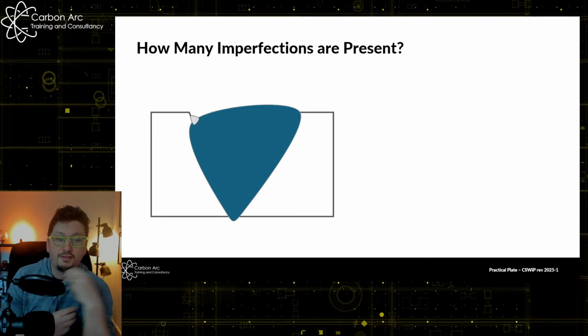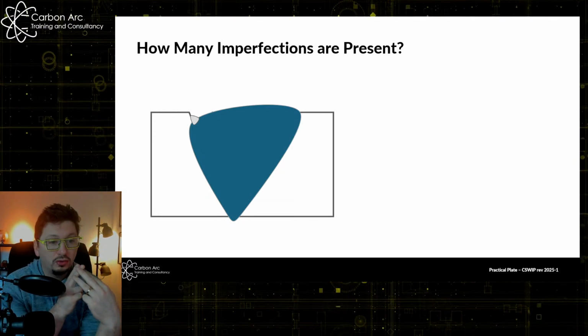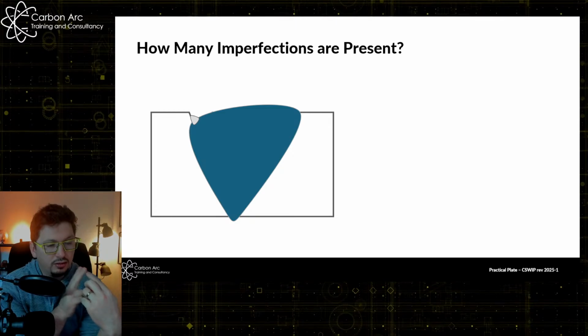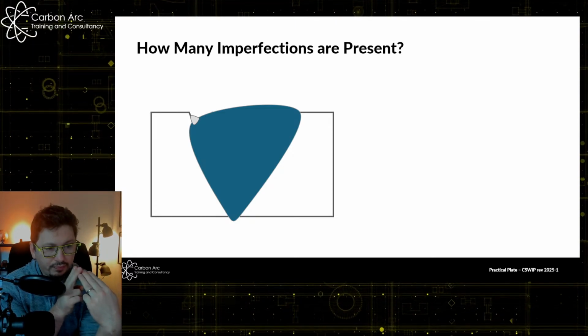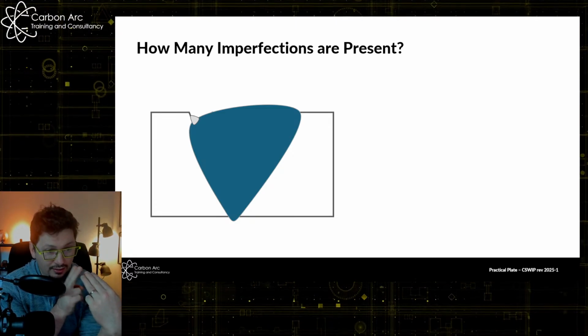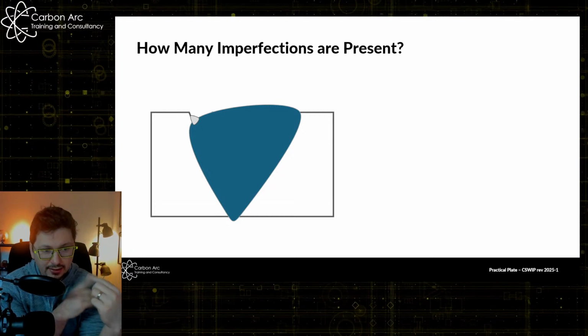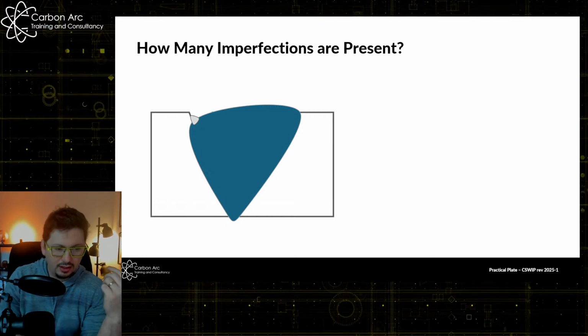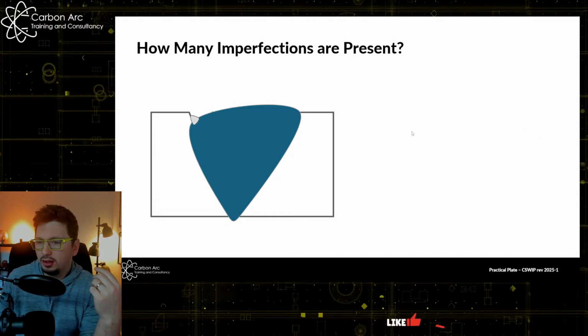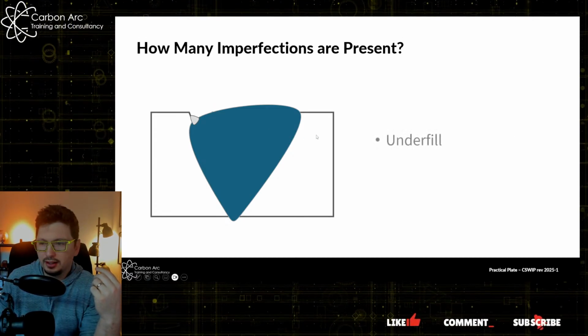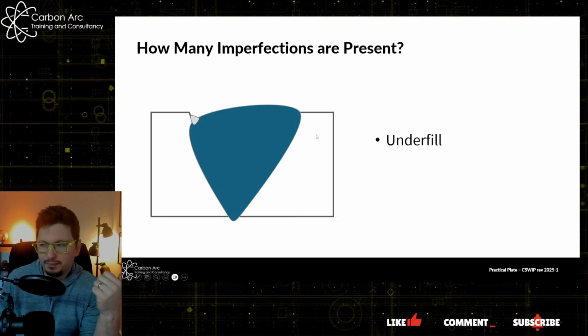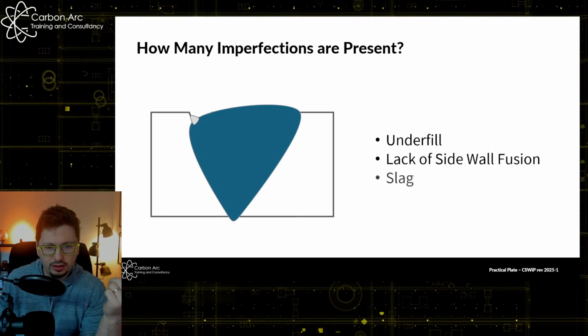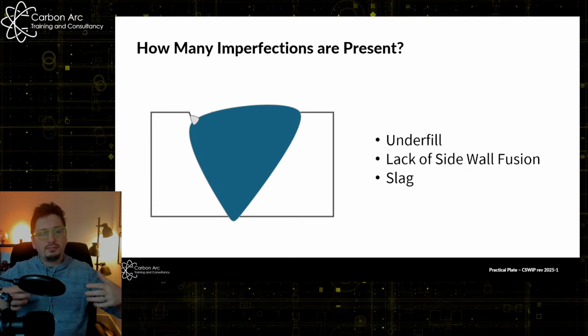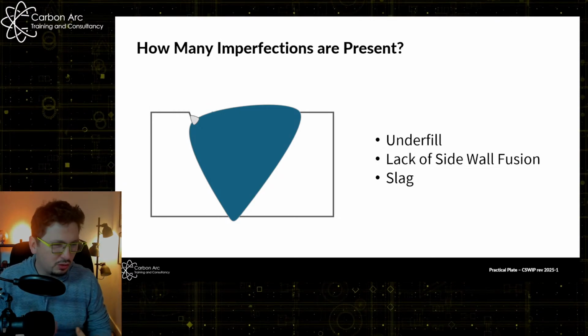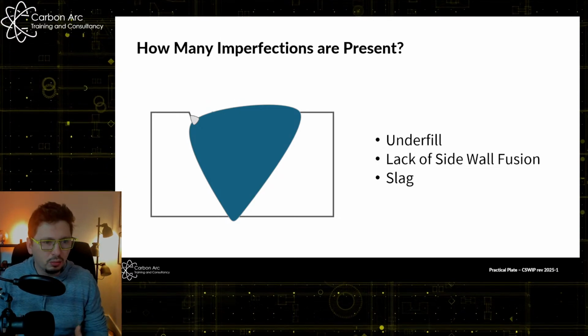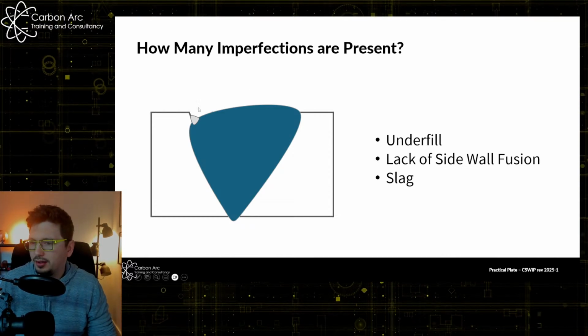Okay. So we've got 3 defects, which are going to need to be recorded separately, and then measured separately and accepted and rejected separately. So I think I've got my underfill, we've got a lack of sidewall fusion, and we've got a slag. And by having all 3, we know there's quite a lot of things going awry with that weld. Okay.